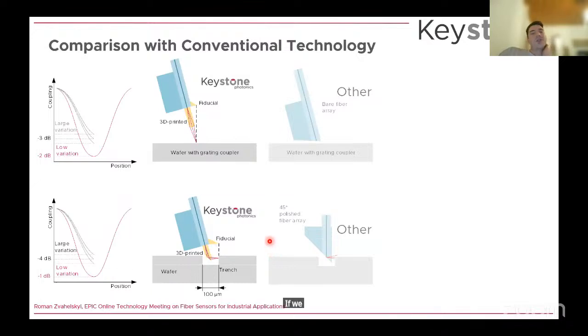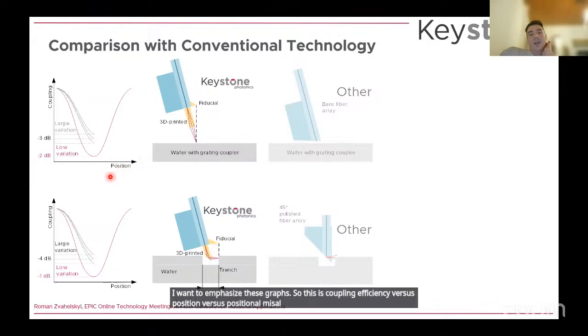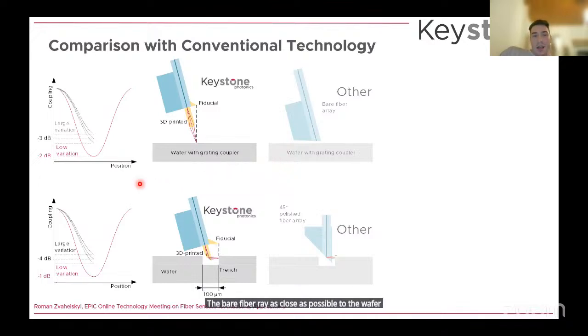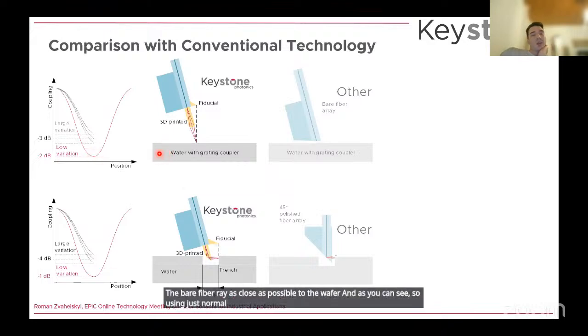If we compare our technology with conventional technology for wafer level testing and for optical coupling, I want to emphasize these graphs. This is coupling efficiency versus positional misalignment, and the red curve represents variation of coupling efficiency using Keystone lensed fiber probes, and the gray curve is just bare fiber arrays, where you move the bare fiber array as close as possible to the wafer. As you can see, using just normal technology, you are prone to variation in coupling efficiency, and our printed lenses have much better coupling efficiency and are less prone to variation. And this is for the grating coupling approach.